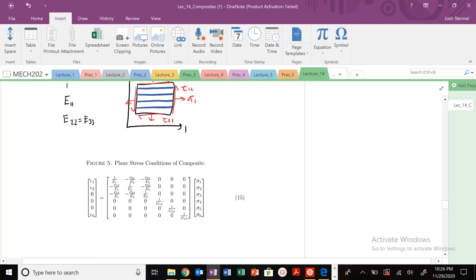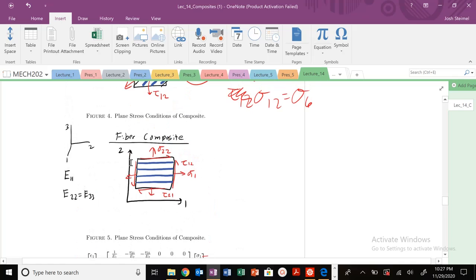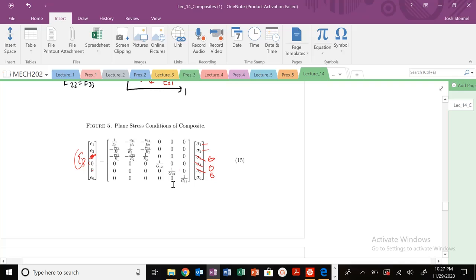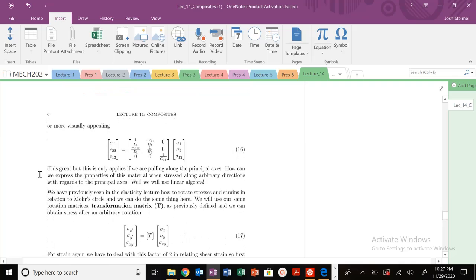Under these plane stress conditions, I know that stresses in the 3-direction are zero. Equivalently, I know that certain strains will be zero, but strain in one direction will be non-zero, and the shear strain will also be non-zero. We can actually simplify — if we're in plane stress conditions, where stress is confined to the 1-2 plane, we can rewrite this matrix in a much more attractive form.